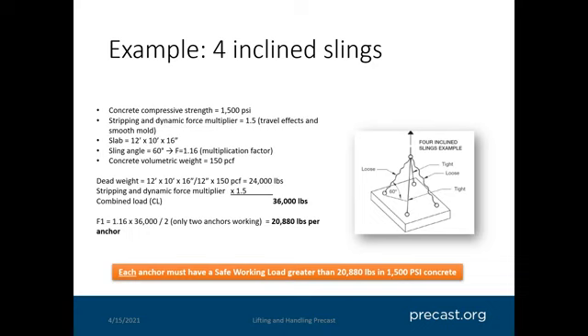Another example of 4 inclined slings. Now we're going to use a stripping and dynamic force multiplier. So same idea. You have a sling angle of 60 degrees here. We got 24,000 combined or dead weight. This thing's been stripped, and now we have a dynamic force multiplier of 1.5. So you have a combined load of 36,000 pounds. Only 2 of the anchors are working because you have 4 inclined slings. So each anchor needs to carry 20,880 per anchor.